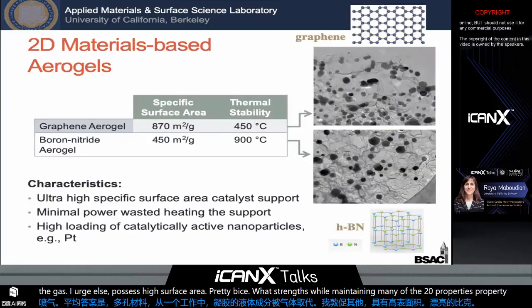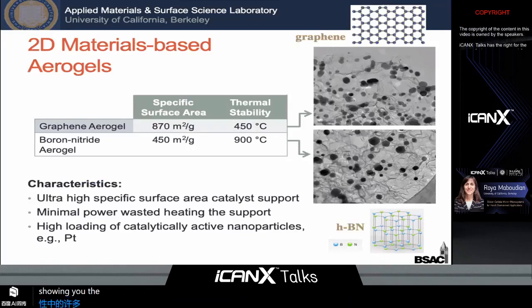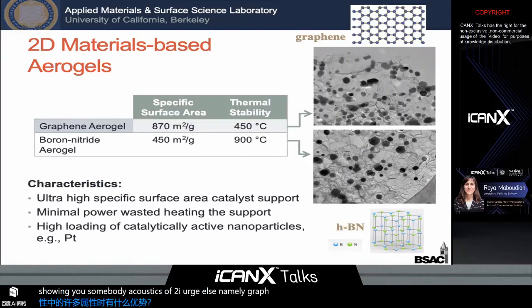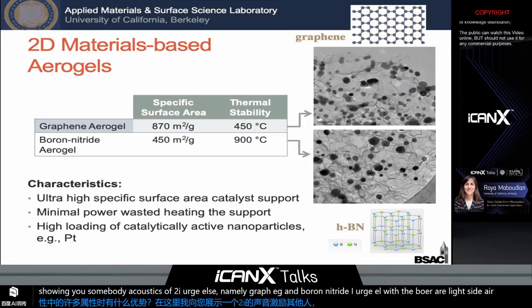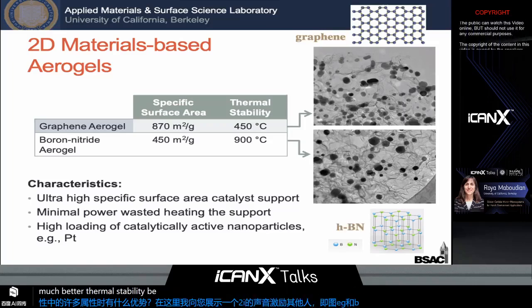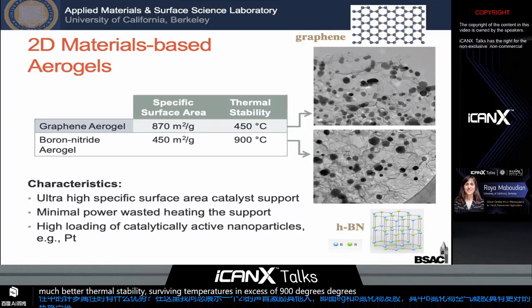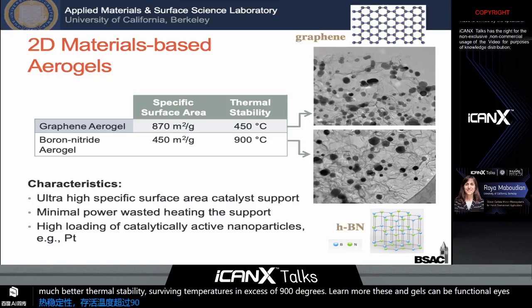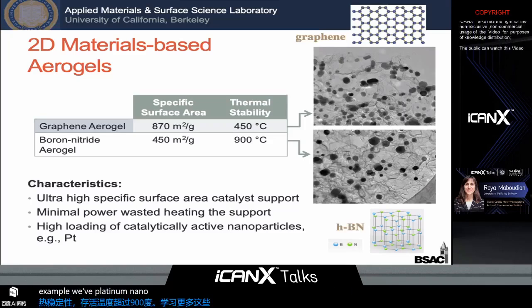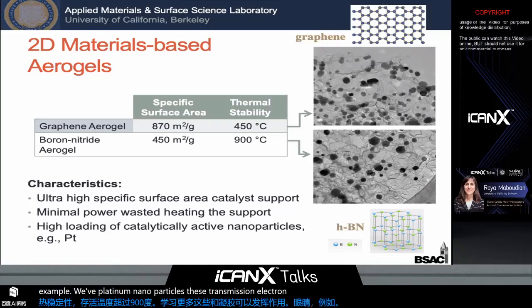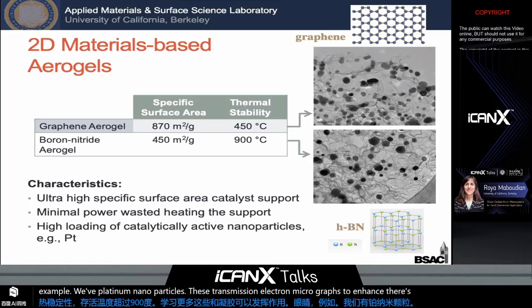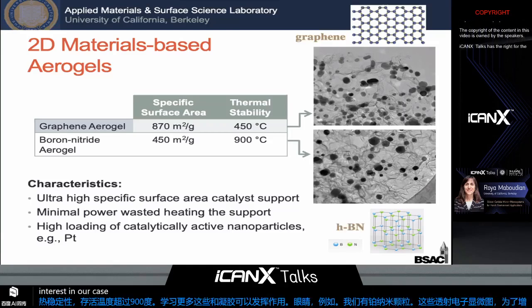Here I'm showing you some characteristics of two such aerogels, namely graphene aerogel and boron nitride aerogel, with the boron nitride aerogel exhibiting much better thermal stability, surviving temperatures in excess of 900 degrees C. Furthermore, these aerogels can be functionalized, for example, with platinum nanoparticles shown in these transmission electron micrographs to enhance their selectivity to the analytes of interest, in our case, to selectively detect combustible gases.